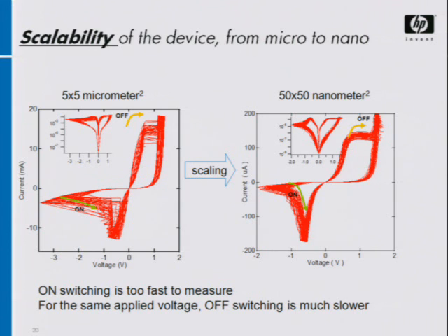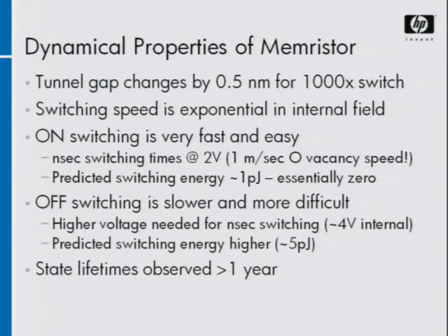As the device gets smaller, it actually gets less noisy, more reproducible. The current scaling isn't there because the larger devices require hotspots, and the smaller devices are smaller than the hotspots of the larger ones, and so you actually start to get good control over what's going on.